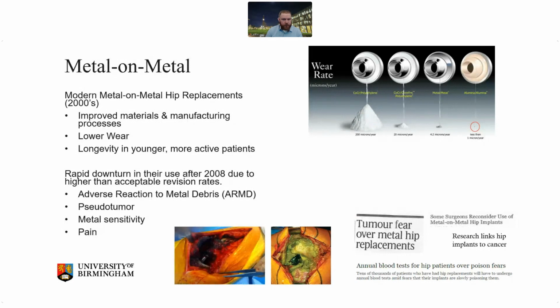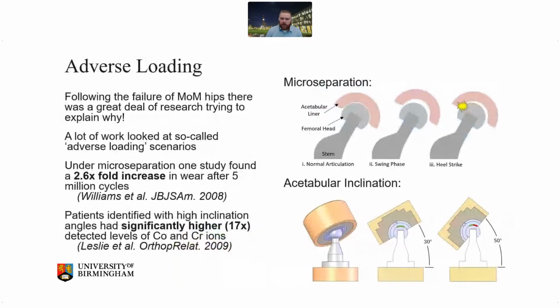So in the aftermath of that, there was a lot of focus on so-called adverse loading profiles in order to try and explain that failure. There were mostly two that came to the fore that have then fed into the standard. So the ISO 14242 Part 4 standard is now about implant positioning in terms of inclination, and also microseparation. So microseparation would either be caused by something like joint laxity or migration of components, where during the swing phase of a cycle, you essentially have the components separate, and then on heel strike, they come back together and result in an impact or a collision across the bearing surface, and then higher wear.